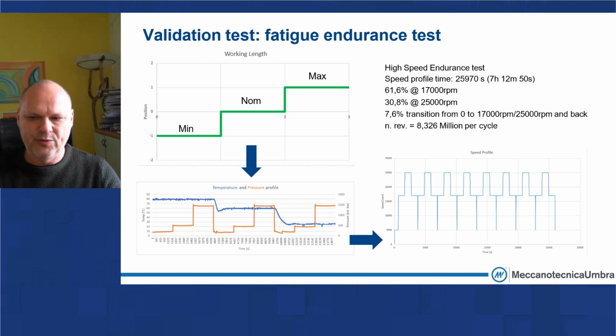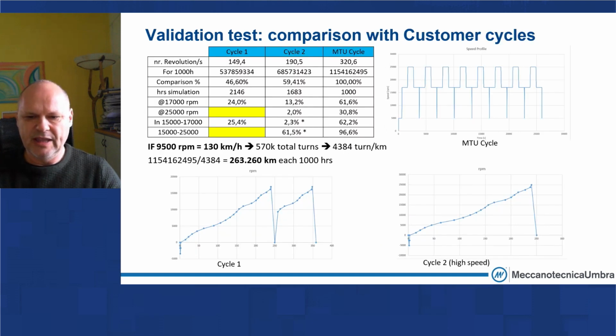So about the performance in the endurance test, the main goal was to understand the leakage rate of this sealing system. We reproduce the working condition in terms of speed, and we define a speed profile in terms of axial movement of the shaft, in terms also of the pressure of the system. So at the end, using the experience with our customer and making a summary of the needs of the sealing system, we define an MTU cycle for this kind of endurance test. We are able, with this cycle, to reproduce in 1,000 hours an amount of 263,260 kilometers.